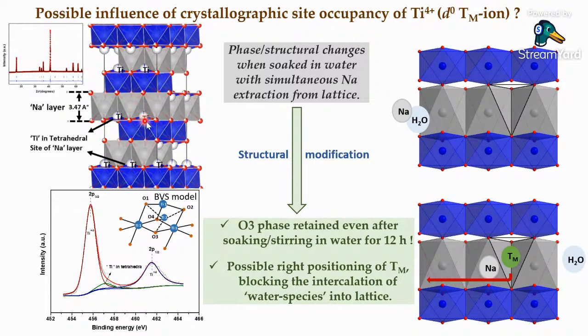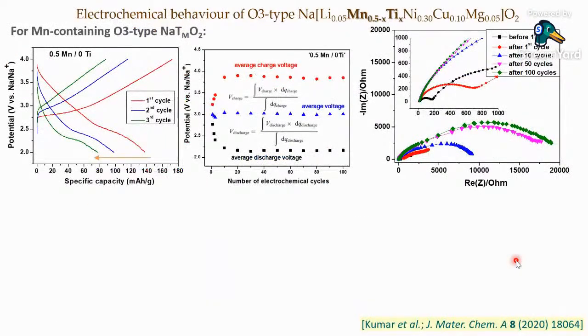So now, if the titanium occupies some of the intermediate tetrahedral sites, then it will block the pathway for the moisture species to come in, and this further contributed towards the improvement in the water stability. Now let's see the electrochemical performance.